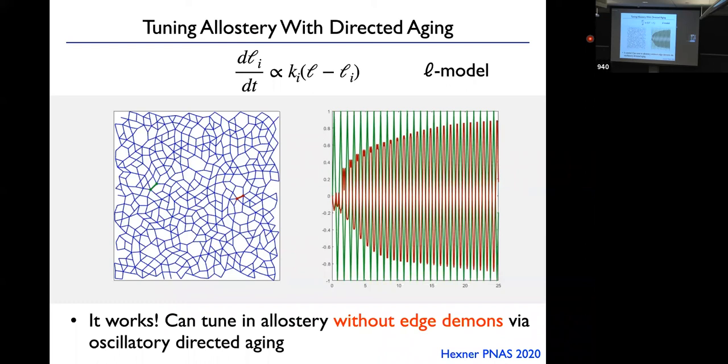And I have to say, in this case it doesn't necessarily get weaker, because of the rule we got: if I stretch a bond, its equilibrium length wants to get longer, but if I compress it, the equilibrium length wants to get shorter. That's what Daniel Hexner is doing.